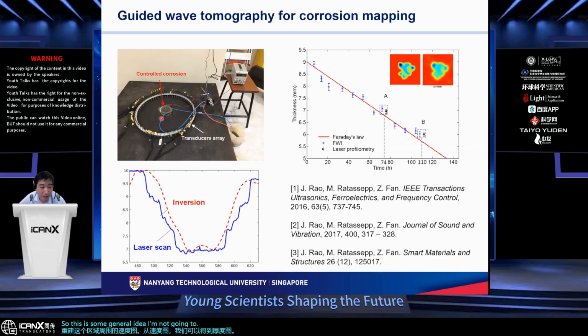I'm not going to go into the details of the exact inversion technique, but I'm going to show you some results. This is after, I think, 74 hours of accelerated corrosion. The blue line is what we measured using a laser, and the red line is what we obtained by inversion using ultrasonic waves. I see a pretty good match. And then this is a line where we can do monitoring. We can further monitor the remaining thickness over time. So at one period of time, we'll be able to get the minimum thickness, right?